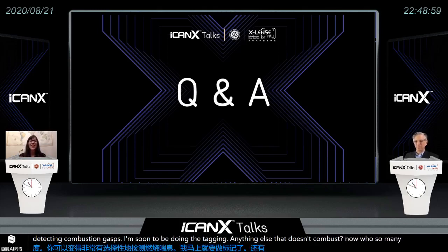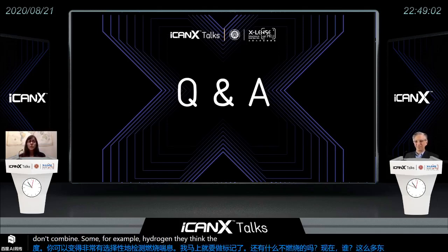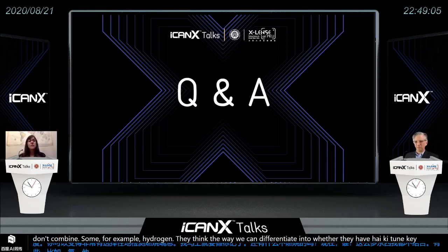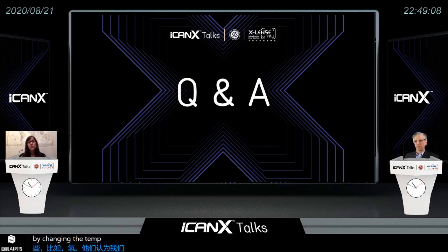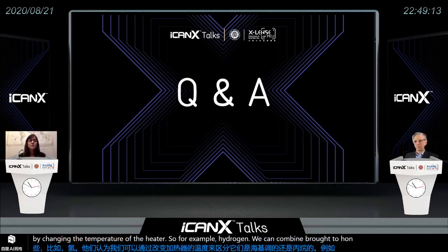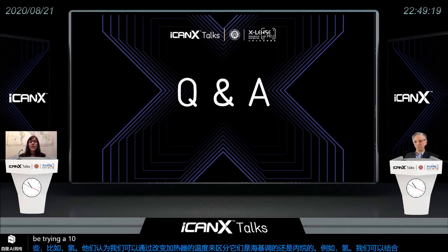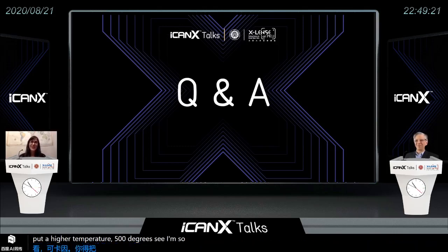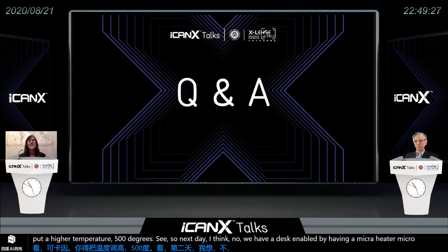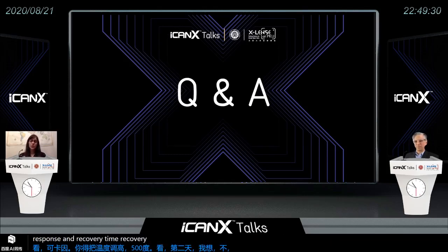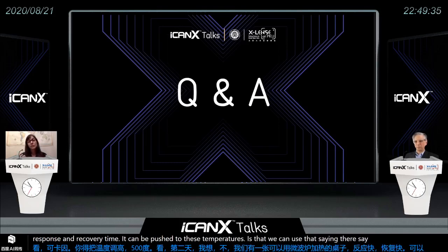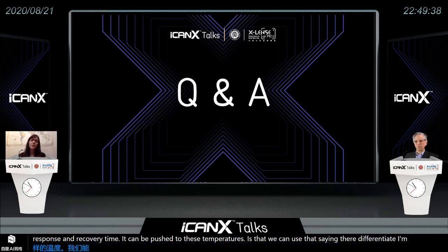So, for example, hydrogen. The way we can differentiate the two, whether we have hydrogen or propane, is by changing the temperature of the heater. For hydrogen we can combust around 200 degrees C. Propane, we have to go to higher temperature, 500 degrees C. So that's the other knob we have. That's the other knob that is enabled by having a microheater that has a fast response and recovery time and can be pushed to these temperatures, that we can use to further differentiate amongst different combustible gases.